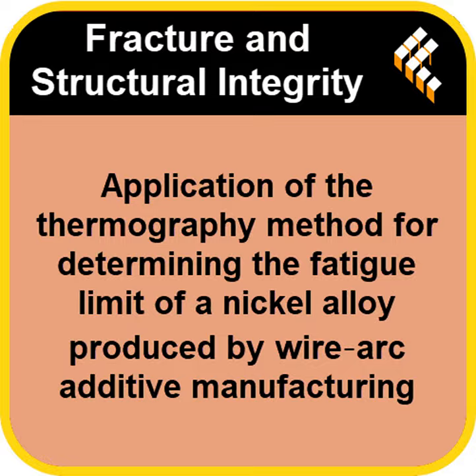That's incredible. So after all that, running a few different analysis variants, how consistent were the final numbers? They were remarkably tight. The mean fatigue limit they got from this accelerated IRT method was 383 megapascals. And the internal variation between their different test runs was less than 0.5%, only 0.46%. To get that level of precision from such a short test is, well, it's astounding for material science.